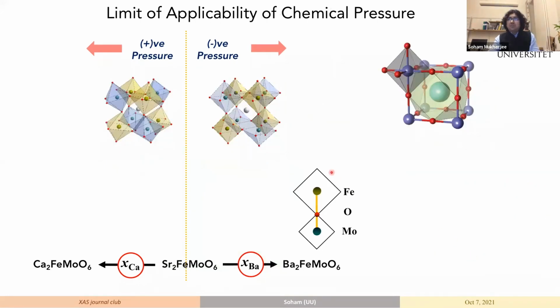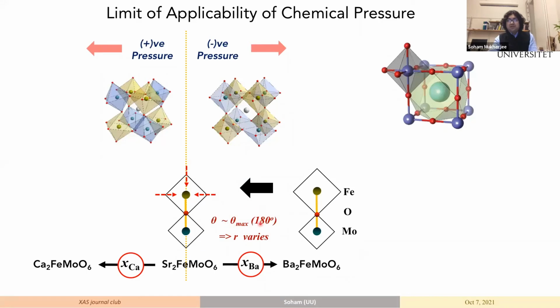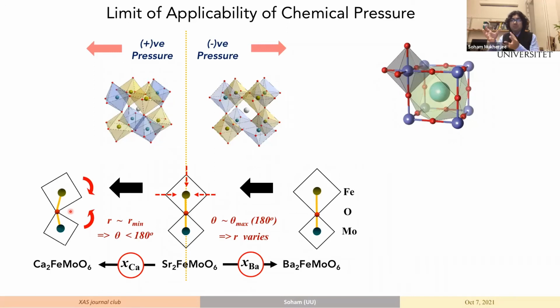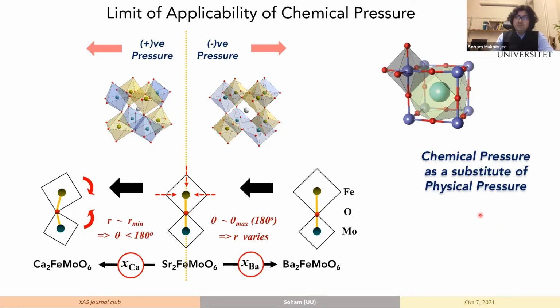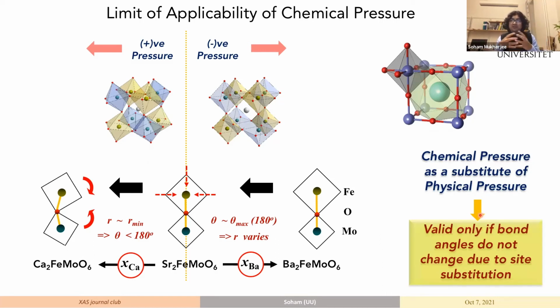So to sum up on this one, when we start from a pure barium, iron, molybdenum, oxygen system, the angles are already 180 degrees. And when you put in strontium, the angles are already constant. So the relaxation of the unit cell is reflected in changing of the bond lengths. But at this particular site, we have already reached the distances iron to molybdenum, iron to oxygen and molybdenum to oxygen have reached their lowest attainable values. And then to accommodate the further shrinkage of the unit cell, they buckle with respect to each other. And so essentially chemical pressure as a substitute of physical pressure can only happen if we can create a system where the bond angles do not change when we are trying to perform site substitution. And this is exactly what we wanted to test.